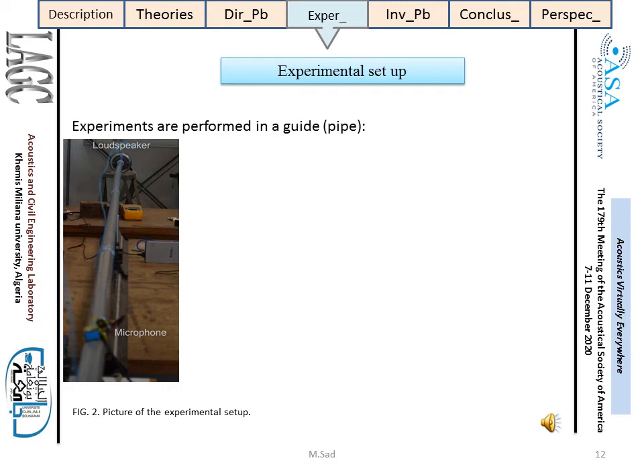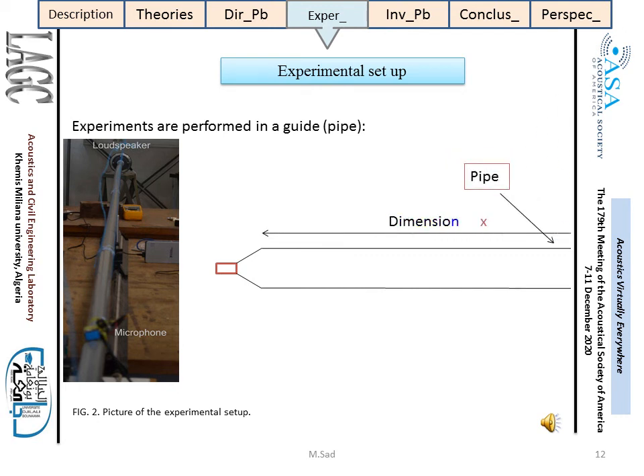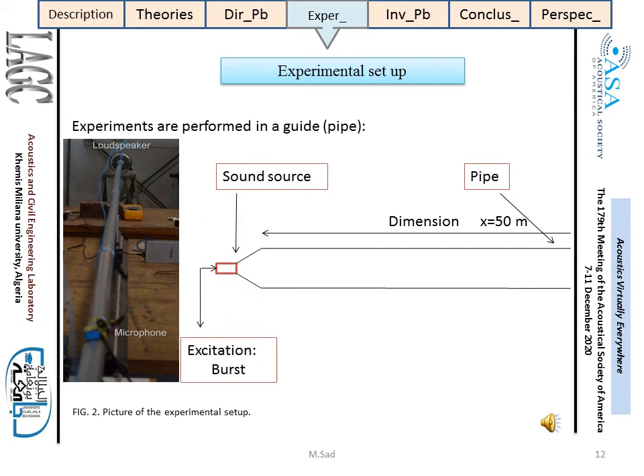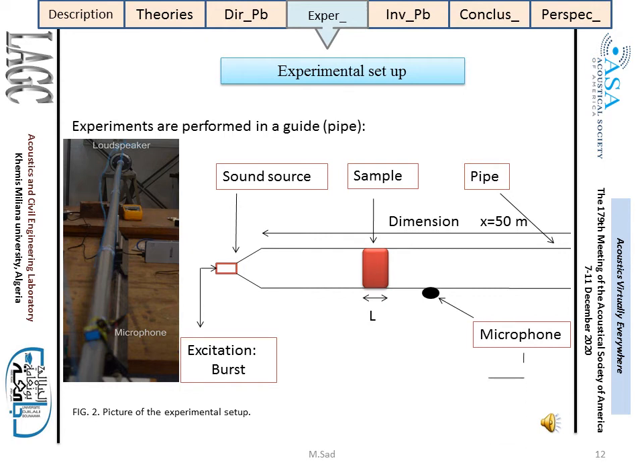Whose characteristics, porosity, flow resistivity, and thickness are as follows. The signals are constructed at center frequency with peaks of 100 Hz, 500 Hz, and 1000 Hz. Experiments are performed in a guide (pipe). The tube length is adapted according to the frequency range desired. The experimental incident signal is measured by putting a total reflector in the same position as the porous sample. The experimental signals are amplified and filtered using a dual column filter.